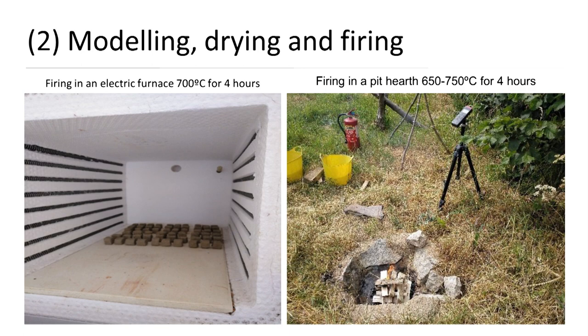Then they were all left to dry for 2 days, and then they were all dried using an electric furnace for 1 hour at 100 degrees to ensure that all specimens were equally dried. Finally, half of the specimens were fired using an electric furnace at 700 degrees for 4 hours, and the other half in a pit hearth between 650-750 degrees for 4 hours.